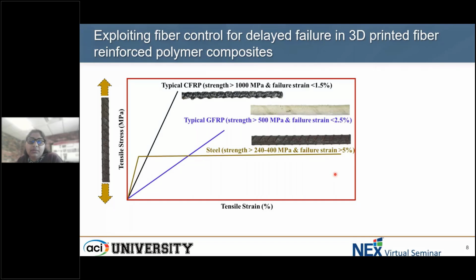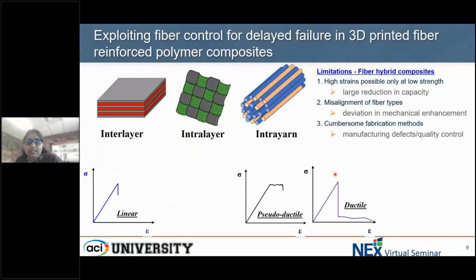Of course, we have conservative design limits, so to take full advantage of its tensile strength, its ductility definitely needs improvement. Multiple efforts were made in the past, especially something called fiber hybrid composites. These composites demonstrate either an interlayer, intralayer, or intra-yarn structure. Interlayer means layers with different types of fibers stacked on top of each other. In an intralayer structure, two fiber types are mixed within the layers and woven into a fabric. In the intra-yarn configuration, the fibers are commingled at the fiber level itself.